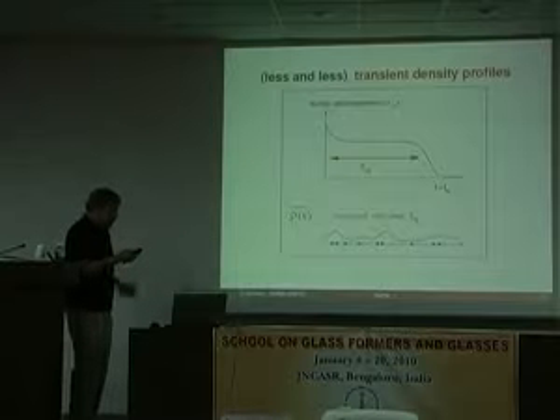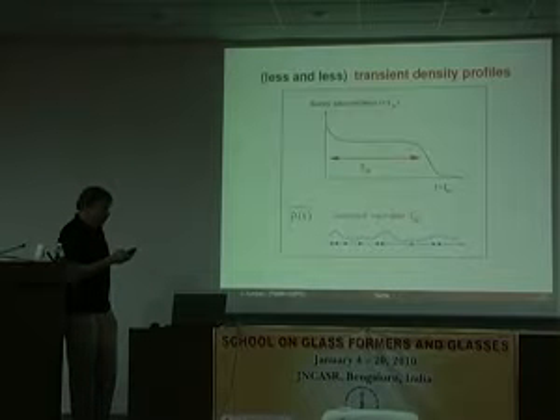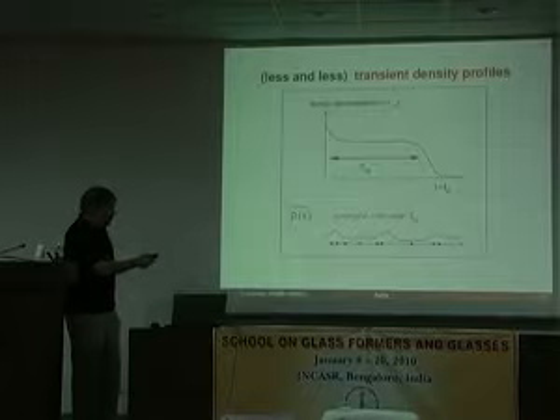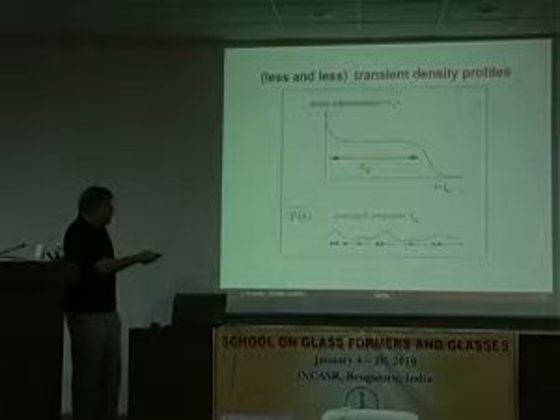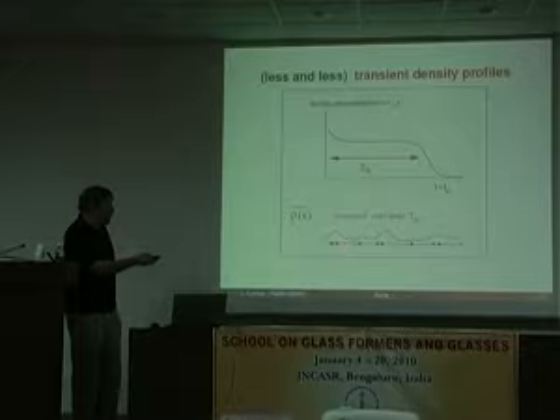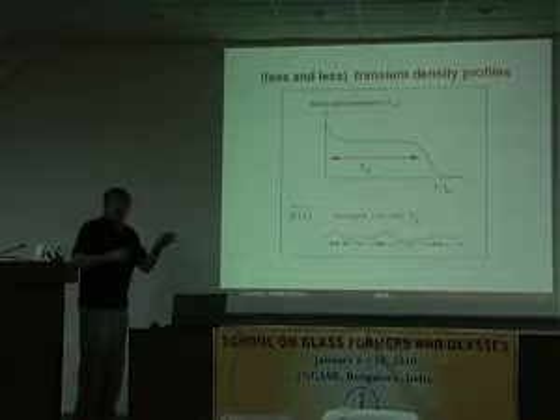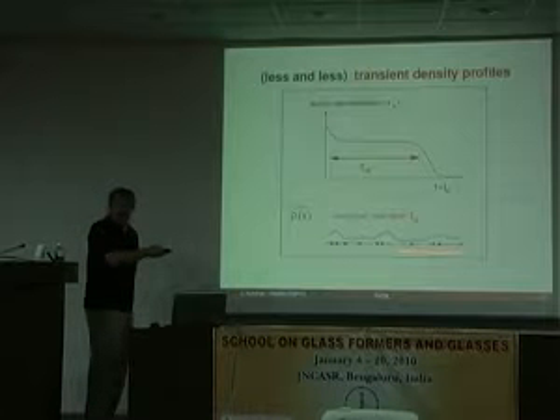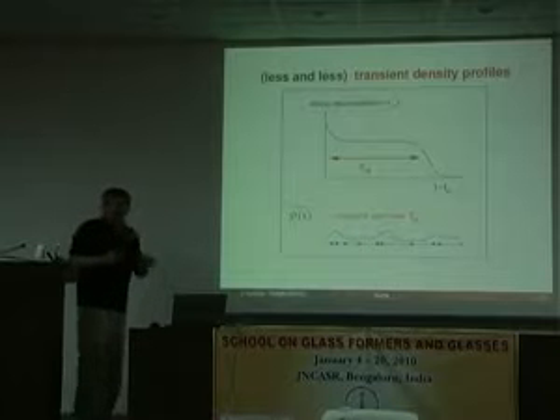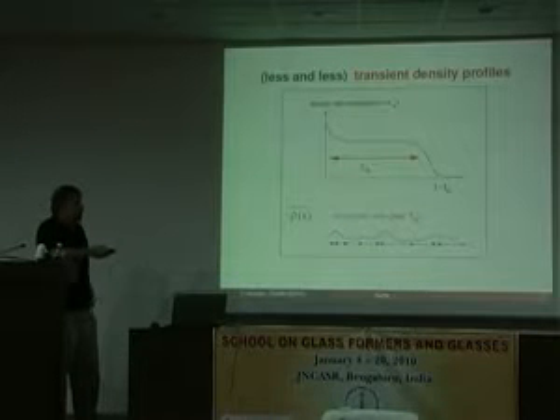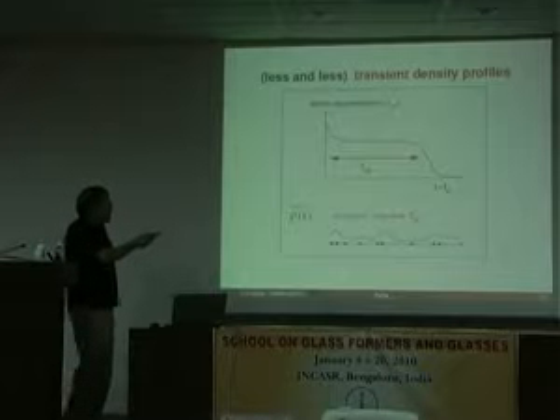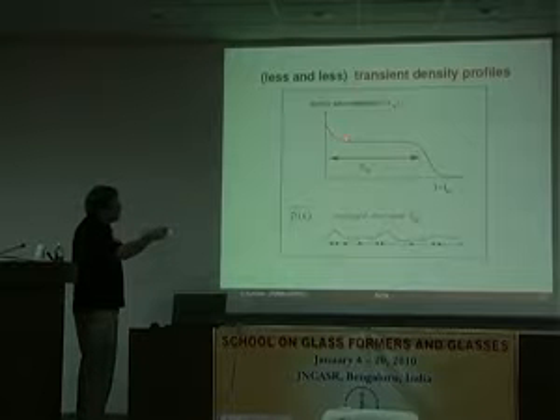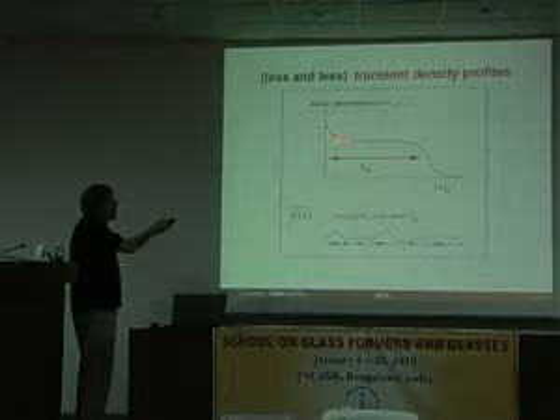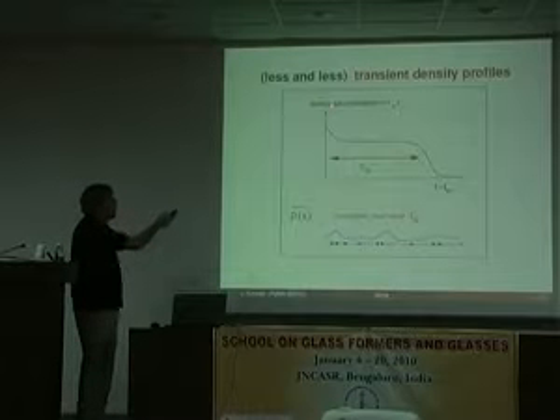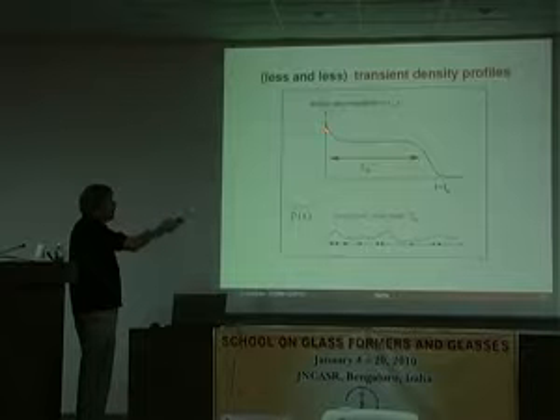I go back to the diagram I did the other day. So you have particles. You have something that resembles a solid in the sense that particles vibrate around positions and then they hop and they exchange, but you have an average density profile that wants to stay there. And so the particle vibration, if you do an autocorrelation function, the fast variations would be the short times.